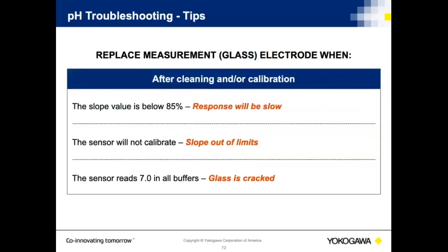Just wrapping up, the slope value below 85%. Hey, when you take the probe and you put it in a 7 buffer and then you put it in a 4 buffer, if it takes 15 minutes for it to stabilize, that means the probe is shot. If you look at the reference, the slope value, you'll probably find that it's well below 85%. The sensor will not calibrate.